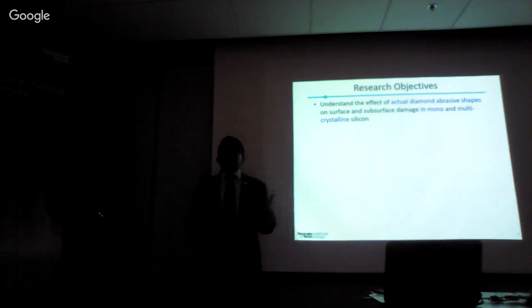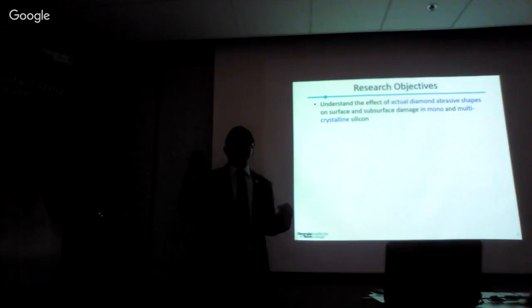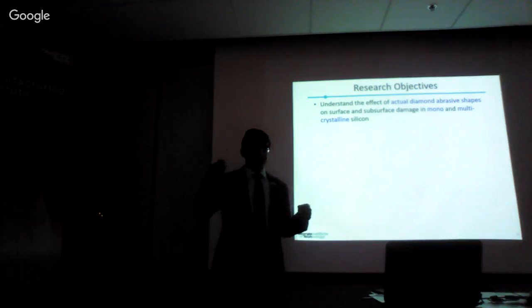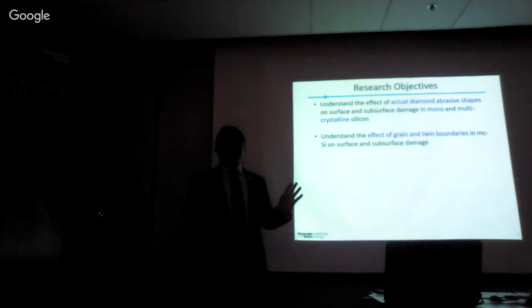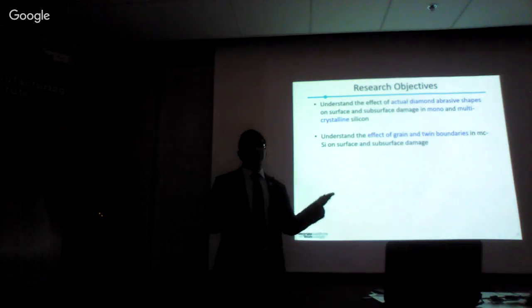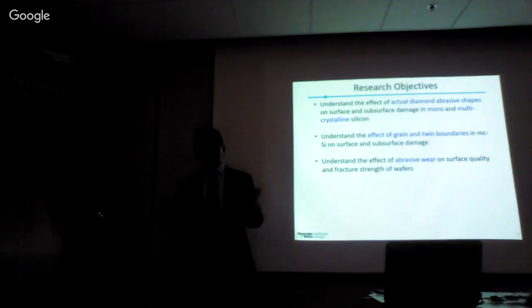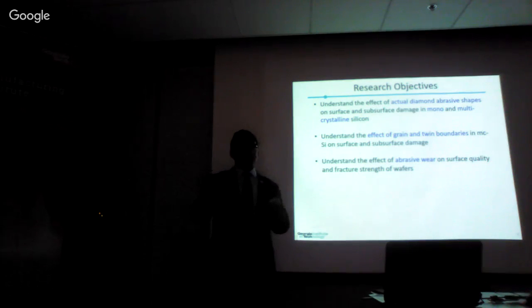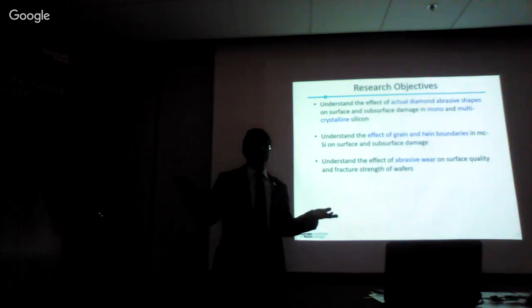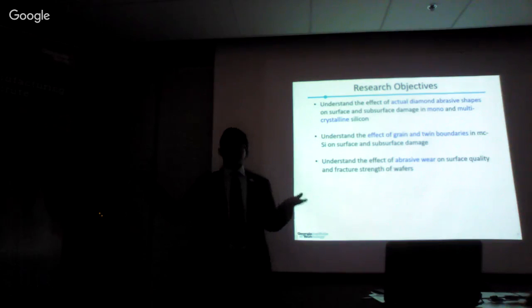Now, this gives us the research objectives based on our literature review, and we see the limitations of prior work. The first research objective is to understand the effect of actual abrasive grit shapes on the diamond wire on the surface and subsurface damage in both mono and multi-crystalline silicon. The second is to understand the effect of multi-crystalline silicon materials, grain and twin boundaries on, again, the surface and subsurface damage on the silicon wafers cut by the diamond wire sawing process. Third, to understand the effect of abrasive wear on the surface and subsurface damage and hence the mechanical integrity of these wafers, which means the fracture strength of the wafers, how it differs with the wear of the diamond wire.